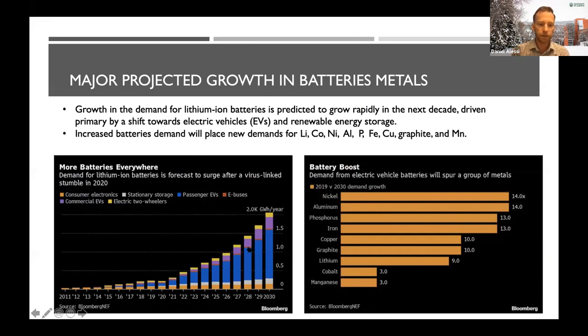You can see we're at 2021 right now, headed towards 2030. Depending on who you talk to, there's potentially a 5 to 10-fold growth in storage need, which translates directly into the need for more lithium to supply the raw material to produce these batteries. Again, here on the right you see different elements that go into batteries. Lithium is one of the big ones, and this is specific to electric vehicles, but we're seeing a 9-fold increase in demand for lithium projected out to 2030.